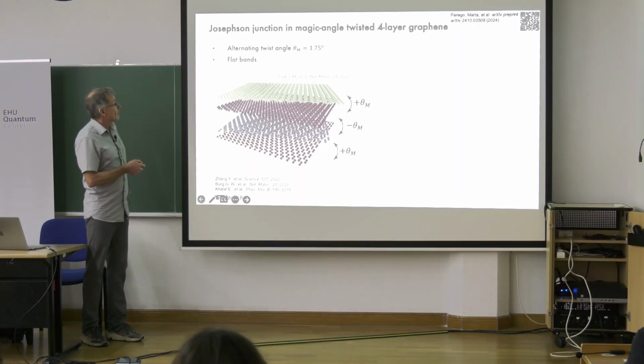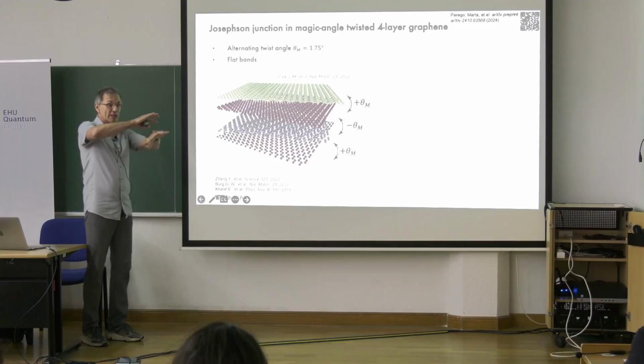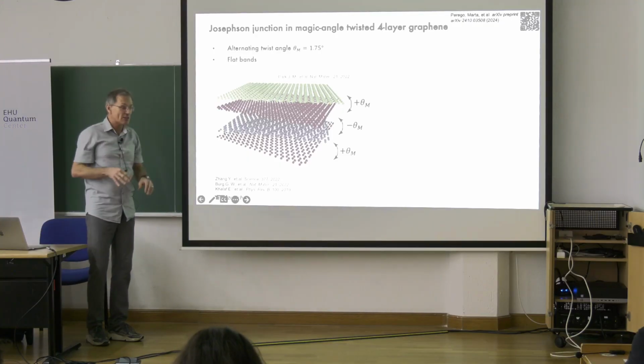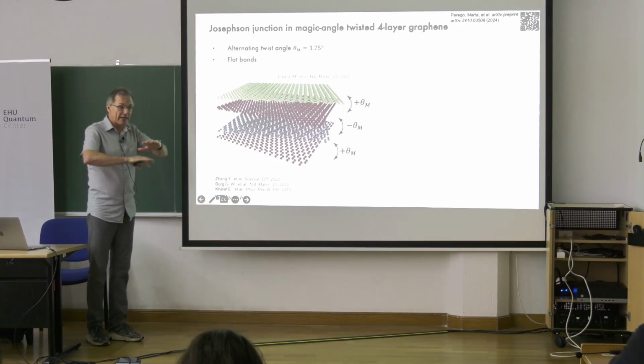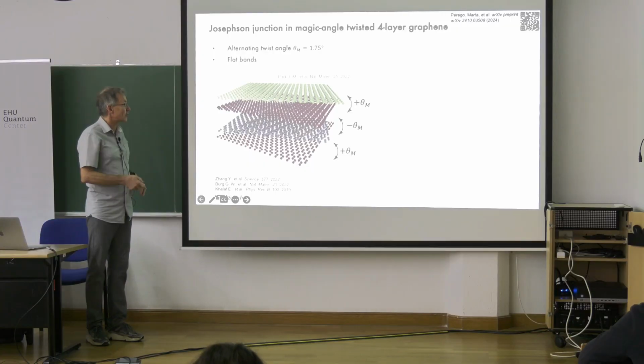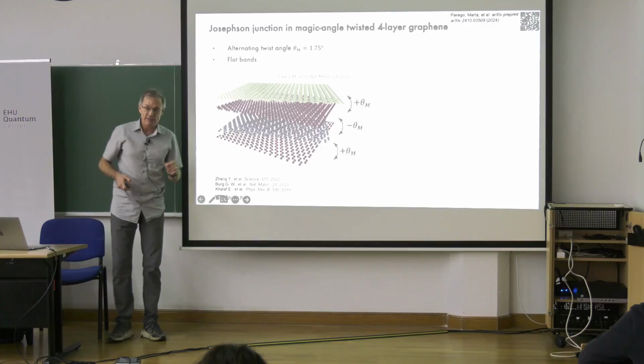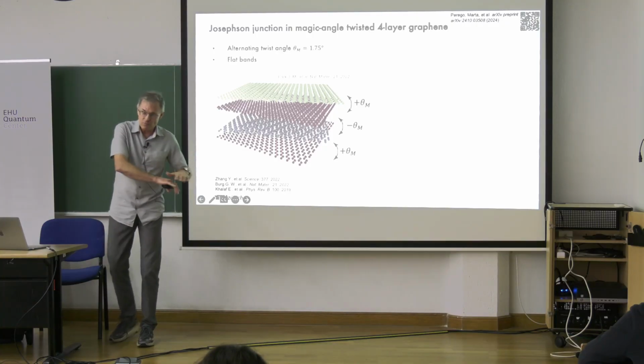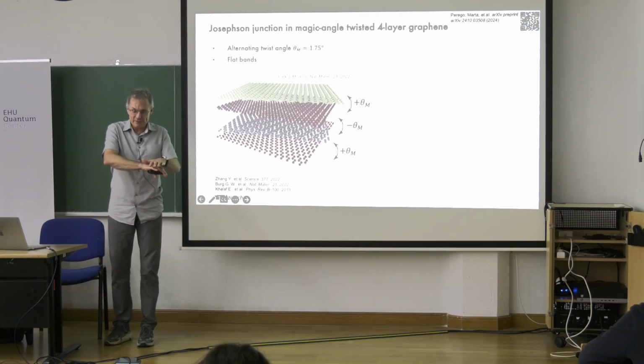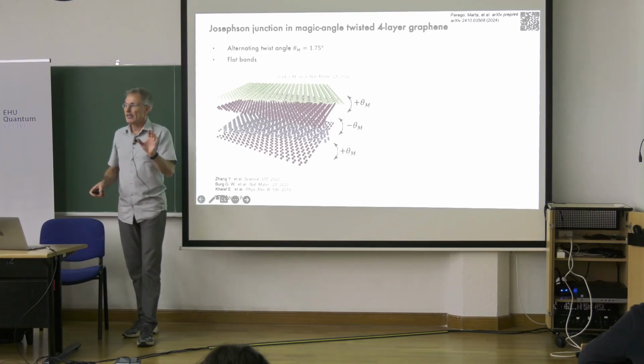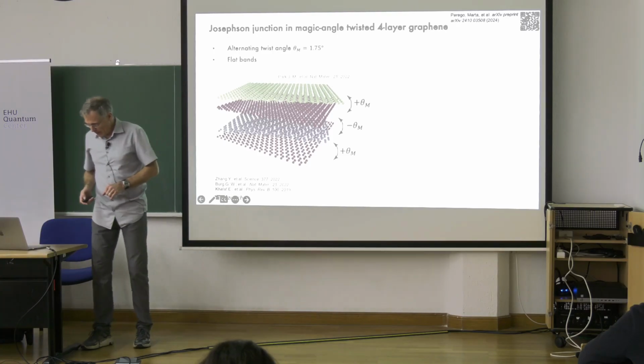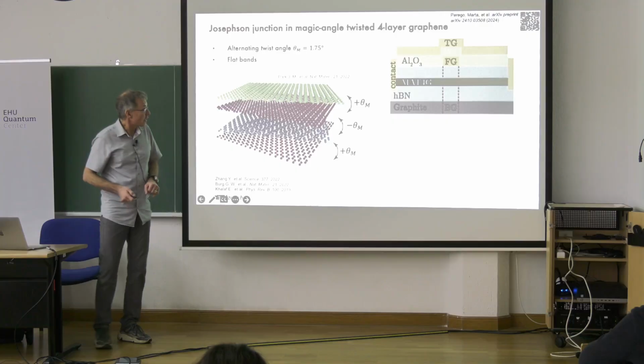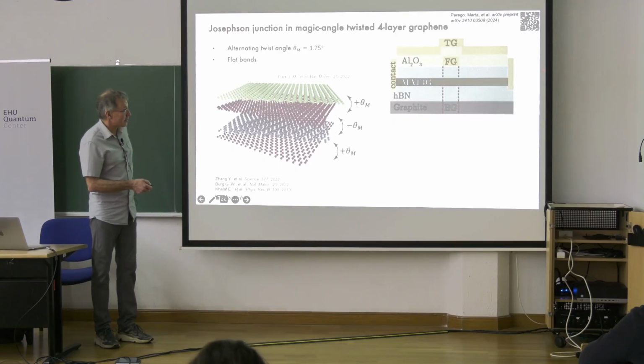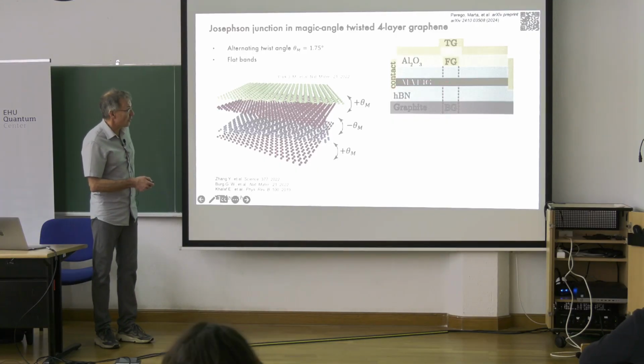She did magic angle twisted 4-layered graphene. Before, I was telling that you take 2 layers and twist. Now you take 4 layers and twist in the opposite direction by another angle, 1.75 degrees. First people discovered bilayer graphene, then 3 layers, then 4 layers, so people are working hard there. So this is 4-layered graphene.